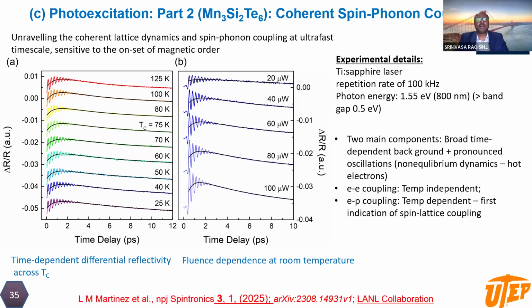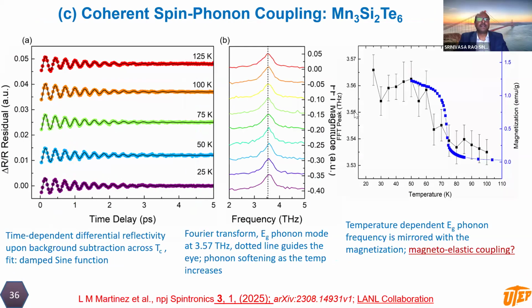We extracted a bunch of numbers, and the most important one is the frequency, how it varies as a function of temperature. Upon taking the differential reflectivity data, we extracted the phonon frequency and intensity, particularly the phonon peak shift here. As you can see, the phonon is shifting as a function of temperature. The trend is shown on the left y-axis, and on the right y-axis we show the temperature-dependent magnetization. So they go hand in hand, and the Curie temperature is about 75 Kelvin or 74 Kelvin.